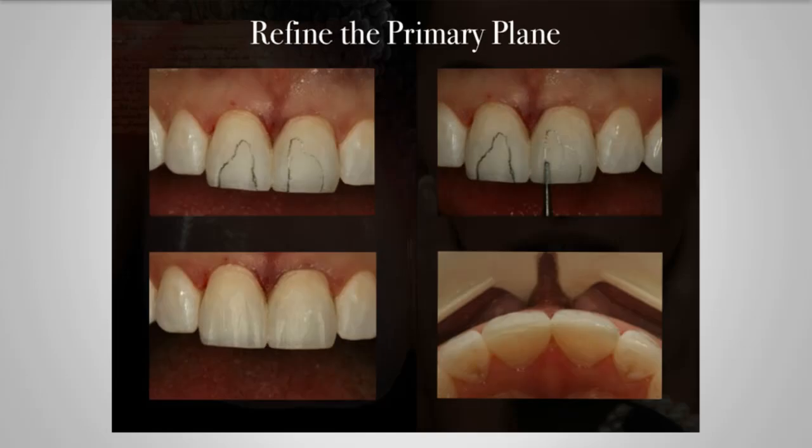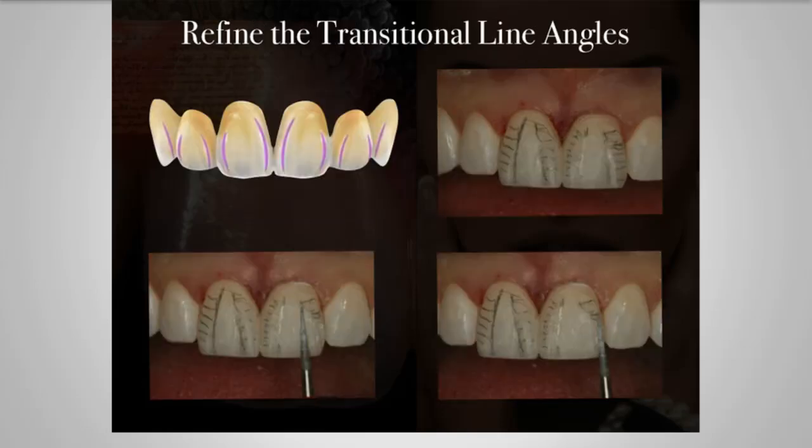When you're using these burrs, it is nice to have an electric handpiece where you can alter the speed. If you're trying to do this at 200,000 or 300,000 RPMs, it's pretty easy to make a mess of it. I tend to knock this down to a 1-to-1 ratio and run this thing roughly anywhere from 50,000 to 100,000 RPMs, depending on how coarse my diamond is, and that could be a nice little pro for those with electric handpieces.